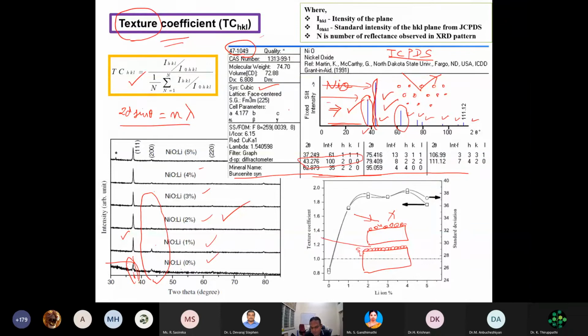So once the X-ray comes inside, even though you give a rotation for the substrate and you try to maximize the exposure, you will see that some other orientation will have higher intensity. So the intensities of the standard pattern will not match for your film most of the time. So you have to identify this is textured growth.